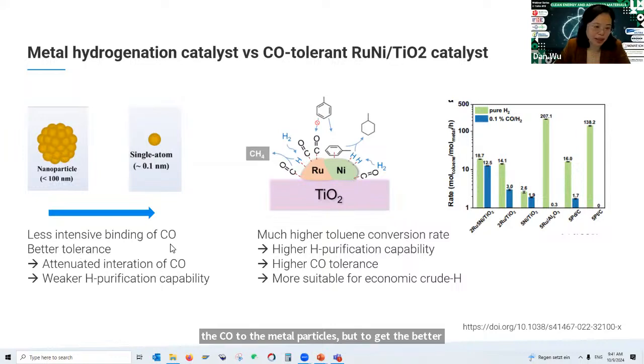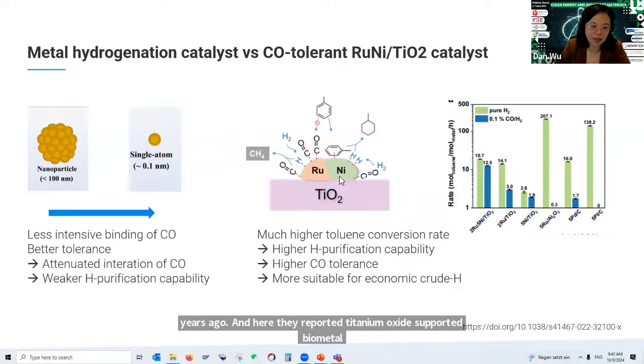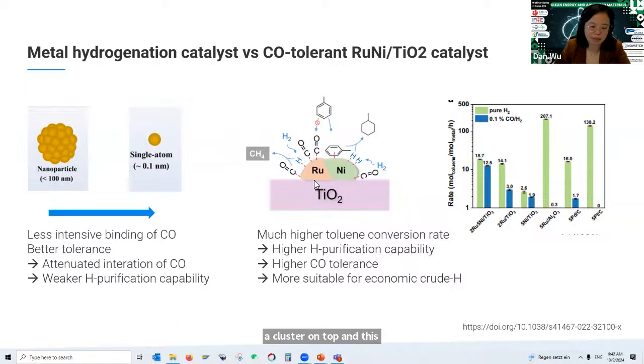But actually, when you get better tolerance of the CO, you also get weaker hydrogen purification capacity. So people have to think about other catalyst supporting materials to get better tolerance of the CO. Here I would like to share a very nice paper published in Nature Communications two years ago. They reported a titanium oxide supported bimetal cluster, based on the nickel element and the ruthenium element.